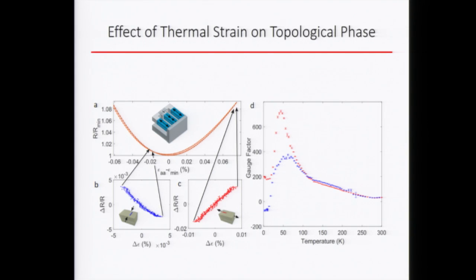topological phase transition. So essentially, you can think that when you cool down, the red crystal and the blue crystal are now in different topological insulating phases. And that might be the reason why people are observing different behavior in different measurements.